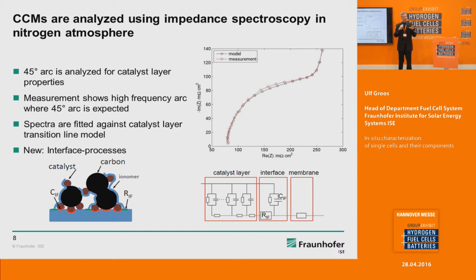What we especially like to investigate the performance of different electrodes is that we do impedance spectroscopy, electrochemical impedance spectroscopy, but we like to do it also in nitrogen atmosphere. If you use nitrogen atmosphere, you can have a close look at the typical so-called 45-degree arc at very high frequencies. And at one point we realized, okay, it's not a typical 45-degree performance, but it's more like an arc. It's not 45-degree, it's more like an arc. And we asked ourselves, why is this?